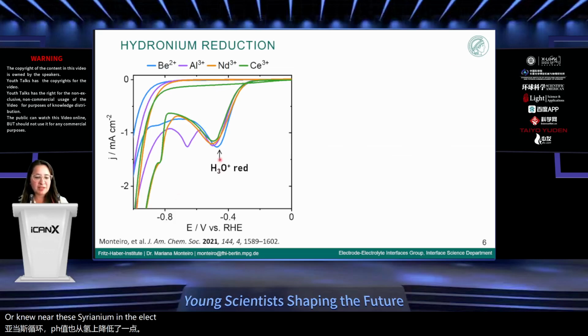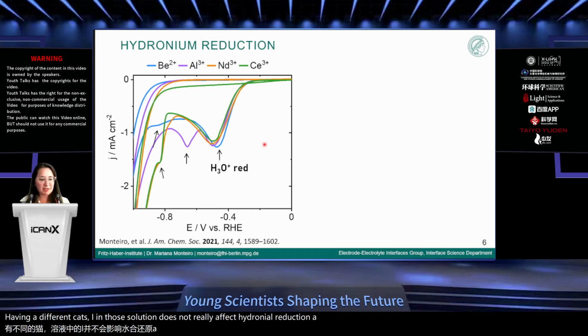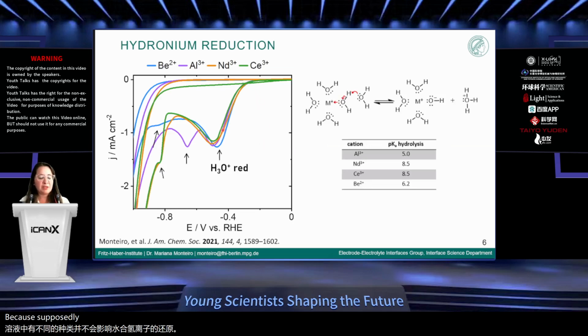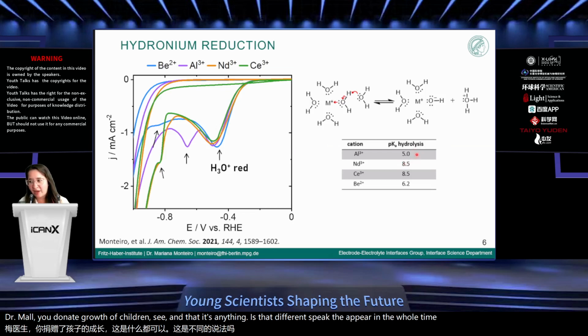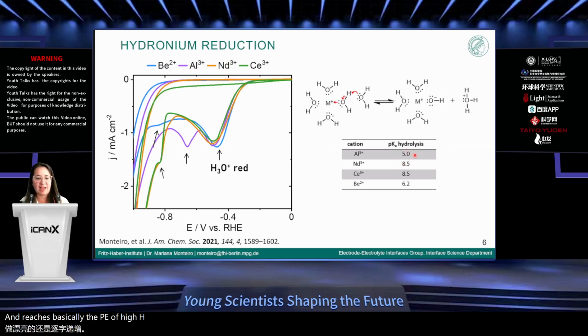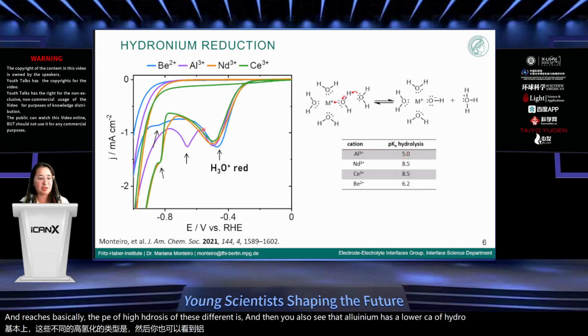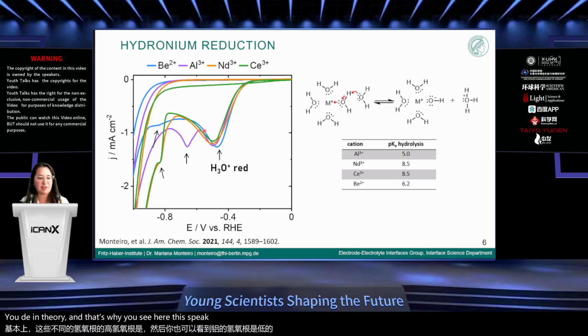supposedly because of the dissociation of the hydronium molecule to donate a proton. What is interesting is that different peaks appear in the voltammetry. These peaks appear once the voltammogram reaches basically the pKa of hydrolysis of these different ions. You also see that aluminium has a lower pKa of hydrolysis than, for example, neodymium and cerium, and that's why you see this peak first. This is basically due to hydrolysis of these ions.